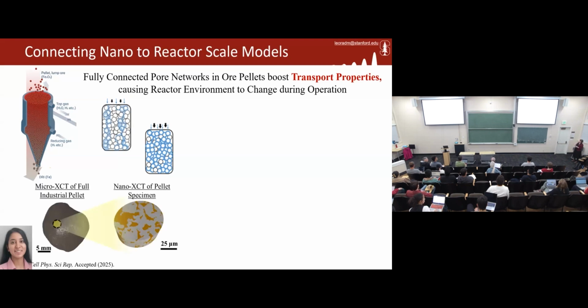So armed with this, she took a micro scale X-ray computed tomography scan of a three-dimensional industrial pellet and was able to characterize the structure of pores that were within that. Then she, with a set of collaborators, was able to get a small piece of a related type of pellet, and then get a view with 30 nanometer resolution as a function of time through the progression of the reaction. How does the three-dimensional porosity evolve?